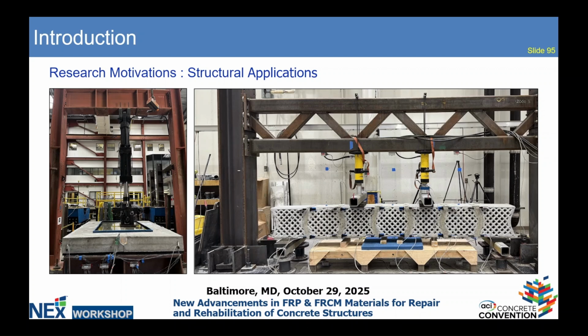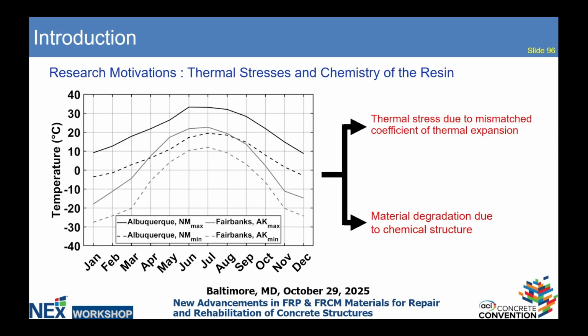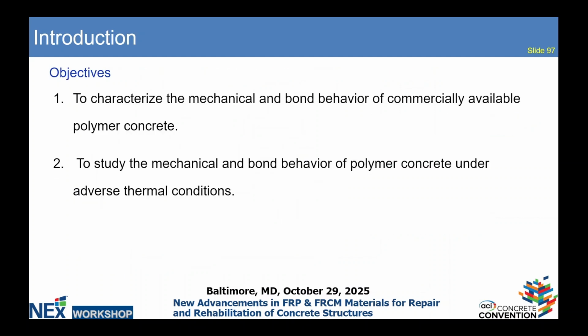But the research that I'm presenting today is a precursor to this research, on the material level. What motivated this research is, as you know, the thermal variations throughout the years, the seasonal ones and the daily ones. For polymer concrete, the thermal variations can have two kinds of effect. One is due to the mismatched coefficient of thermal expansion between the polymer concrete and the regular concrete, because since those products are used in the joint, the coefficient of thermal expansion is important. And on the other hand, there can be reduced performance due to the material degradation of polymer concrete because of temperature. So we wanted to capture these two effects in our research. The objective was to study the mechanical and bond behavior of polymer concrete under thermal stresses.